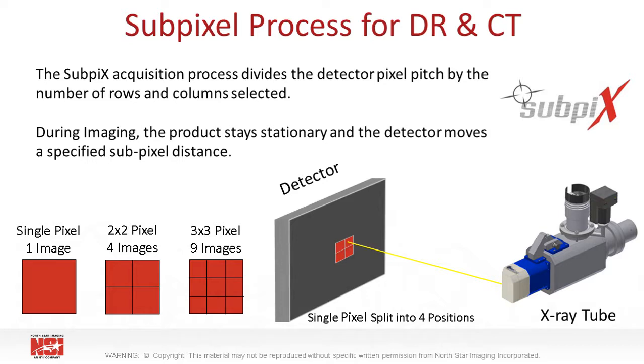This is especially important when we're talking about using high energy systems with larger focal spots and lower geometric magnification, such as with a minifocus X-ray or a linear accelerator. The lower magnification provides for larger field of view for a given resolution, and these larger focal spot tubes can produce higher photon counts, allowing higher frame rates for faster acquisition, which can help balance the time in acquiring the additional subpixel images. Subpix is also used extensively to push image resolution even higher with microfocus tubes and geometric magnification.